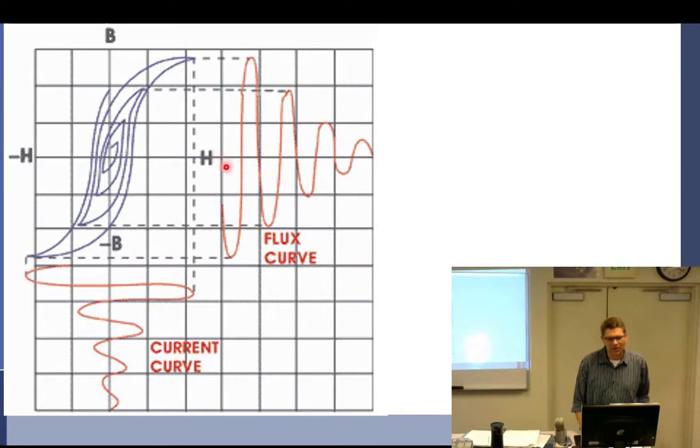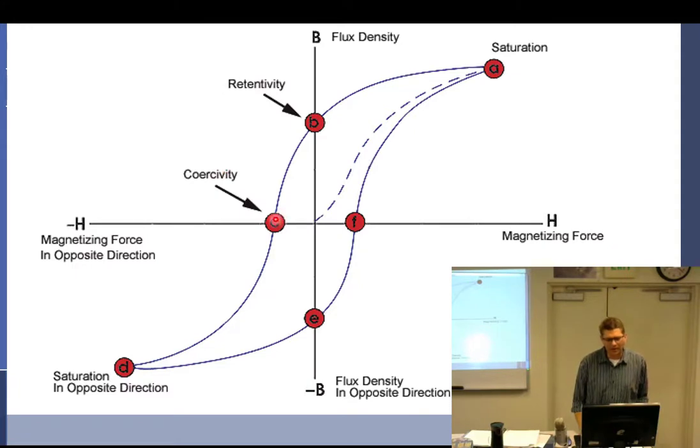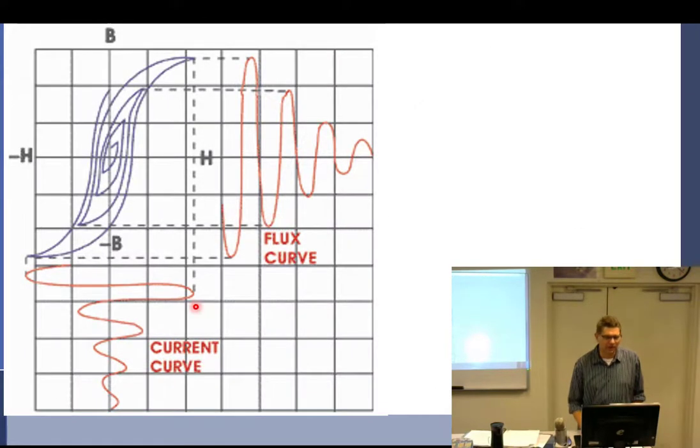So this explains why a diminishing current does in fact demagnetize something, because you would kind of look at it and say, well, wait a minute, if I decrease the current, isn't that enough? Doesn't that then not overpower? Do I not have enough coercive force to bring it back the other way? But it doesn't actually work that way. It really does work like this. It'll bring it backwards, then the other way, then the other way, and it actually starts following this curve until you get it right back to 0. So that's why it takes longer to demagnetize. Yeah, because you have to do it over and over.